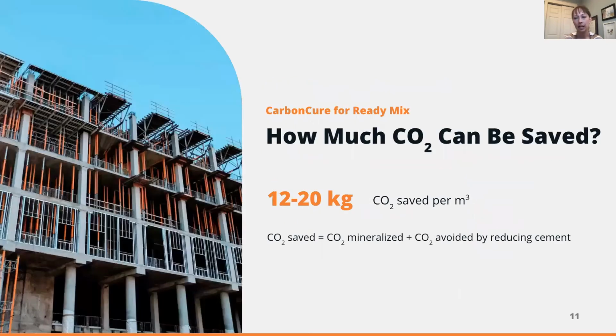At the end of the day, the concrete that's delivered to construction sites meets the same quality and control standards, the same compressive strength, but with a reduced carbon footprint. The amount of carbon that can be reduced really depends on a number of factors. It's very mix specific. It's typically between 12 to 20 kilograms of CO2 per cubic meter that can be reduced. This typically represents about a 5% reduction in the overall carbon footprint.